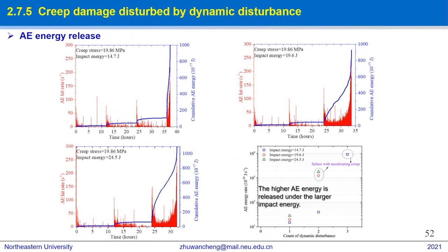The AE behaviors during the creep impact experiments with different impact energies are shown in this figure. Affected by the first dynamic disturbance, both the cumulative AE energy and AE hit rate consisted of a primary phase and a steady state phase. Unlike the result with the impact energy of 14.7 joule, both the cumulative AE energy under the impact energies of 19.6 joule and 24.5 joule showed trimodal behavior affected by the second dynamic disturbance, which is consistent with the behavior of the strain curve as shown in the last figure. All of the AE energy rates exhibited an increase with the increasing count of dynamic disturbances.